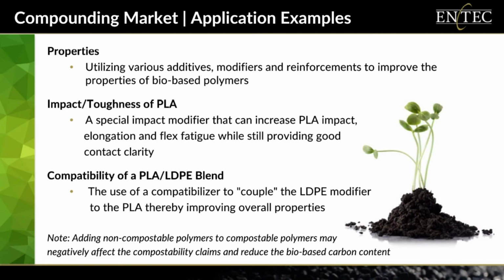But as I mentioned, one of the shortfalls with PLA is its inherent brittleness, which necessitates the need to compound in impact modifiers. Entec offers several impact modifiers that can be utilized, and we even have special modifiers that can increase the impact, elongation, and flex fatigue and still provide good contact clarity in a PLA compound. Another example is utilizing a compatibilizer to improve the properties of a PLA LDPE blend. LDPE has been used to improve the flexibility of PLAs, but LDPE is not compatible with PLA. Compounding in a compatibilizer will better tie together the PLA and LDPE and improve the overall properties of the compound.